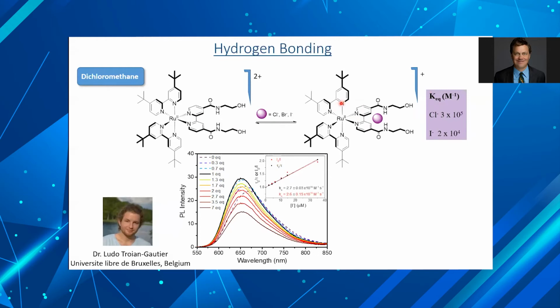These molecules and many of the dyes used in dye-sensitized solar cells luminesce. So if you excite them with light, you can see intense photoluminescence. And what Ludo found was that when he binds the halide here, it actually enhances the luminescence. And once there's one equivalent here, as he goes to higher concentrations, he could see the luminescence quench. And the excited state lifetime did that as well. So that was curious to us, and it made us wonder why.